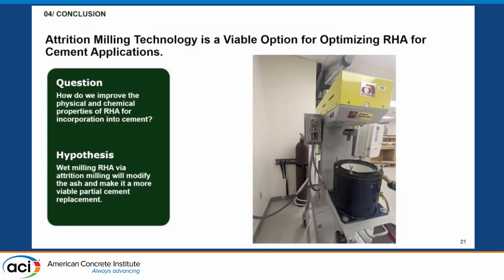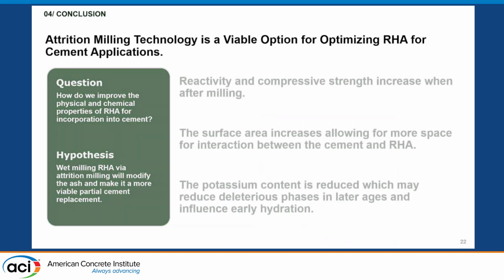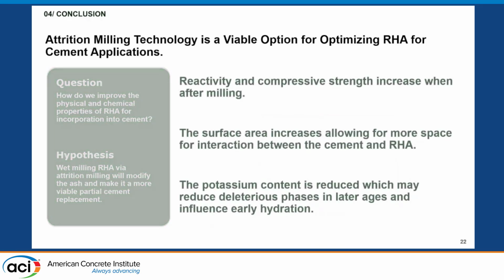So to conclude, the attrition milling technology is a viable solution and addressed some of these questions of how do we kind of better incorporate rice hull ash into cement. And something that I did not note earlier is that the cubes that I made, I didn't end up using any admixtures for, and I did about a 30% weight replacement of the material with rice hull ash. And so the workability is something that I'm going to be further exploring, but it substantially improved as well.